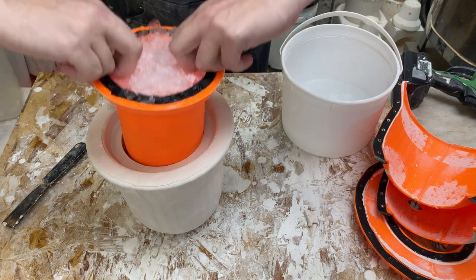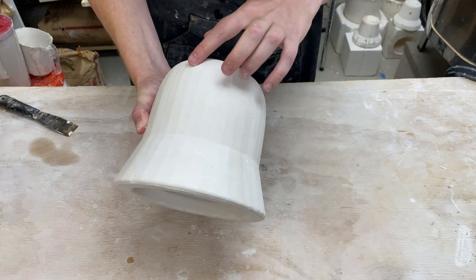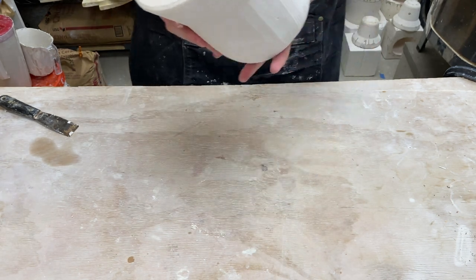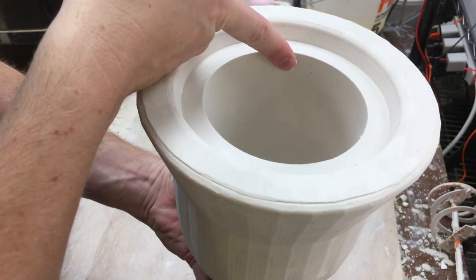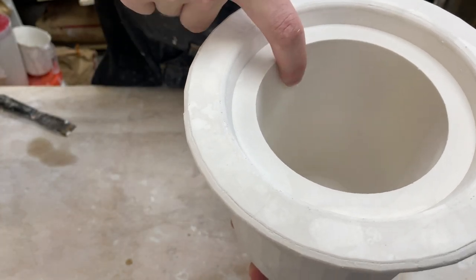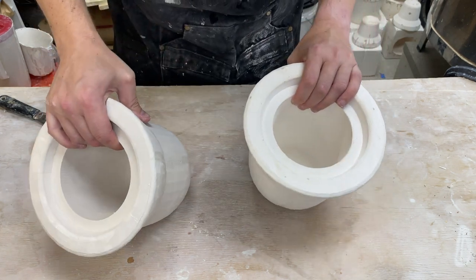Here is our mold. As I mentioned, there are definitely a few pinhole bubbles on the outside. Looking at the inside, I am seeing some down in there - they aren't through the surface, I don't think, but they're just below the surface. I see some farther down as well. So compared to the previous mold, is it obviously better? I don't think the answer is yes, which is a little bit surprising.